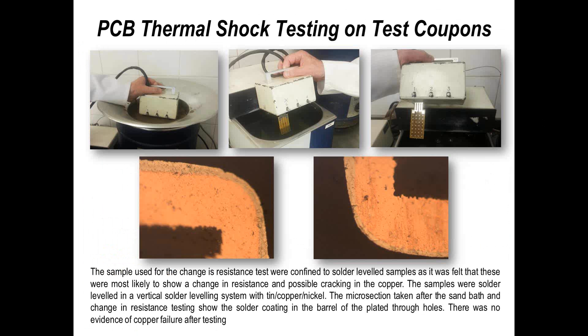Thermal shock testing is taking a board, measuring the resistance and then seeing the change in resistance when you put it into water at ambient temperature and then a liquidized sand bath at 260 degrees C. Both of the microsection photographs you see on the center of the page are after testing. The quality of the boards was very sound with no problems associated with the aging. The reason for doing this is to see the effect of boards before and after soldering to make sure that nothing we've done has impacted the quality of the boards.